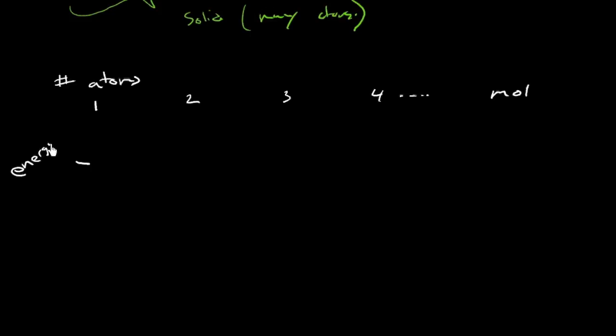And what do the energy levels look like? And let's just look at a simple case of one energy level. Say it's 1s or something. So this is the energy level or the state available for an electron. If we're just saying, OK, compare this particular state, say it's 1s. Then what happens when you get two atoms coming close to each other, and their 1s electrons, or the electrons in whatever state it is we're looking at, get very close? Well, they interact. And in fact, there's a splitting in the states, such that they're not degenerate.